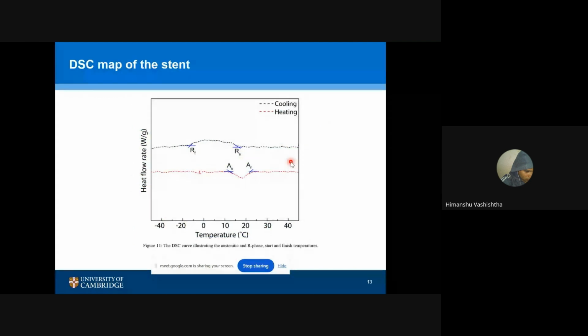Now, DSC maps, differential scanning calorimetry. During my start of the talk, I told you about the austenitic finish temperature or martensitic finish. So that's the heating cycle, that's the cooling cycle, right? The black one is the cooling, this red one is the heating cycle. So if I'm heating my material - heating means it's not really heating, it's up to 25 degrees only, right? So if I'm heating it, let's say here is the martensitic phase or the R phase, whatever you call it, because either you are finding R phase or martensitic phase if you're not deforming it extremely.